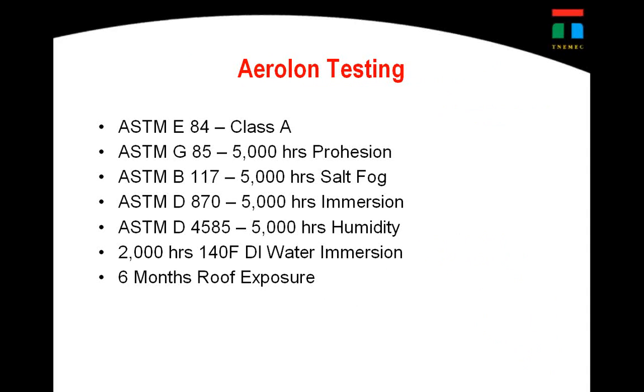This was back about 4 years ago. And we started running on this Aerolon technology, and I'll show it to you in just a second. But we realized we had to meet a couple of different targets from a coating perspective, but also from an insulation perspective. And what we're talking about now is not only does the material have a very low K value, you're talking about a K value of 0.035, which is actually lower than spray foam. So this silica created a very thin, highly efficient thermal barrier.